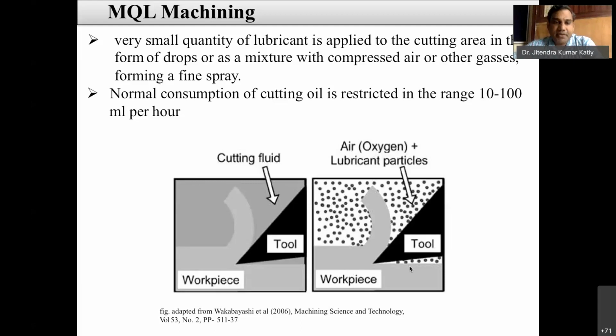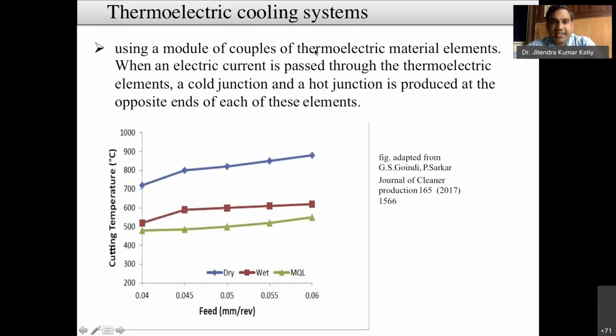So minimum quantity lubrication in terms of thermoelectric cooling systems is also very important. At the cutting temperature, you can see that even if you increase the feed, the cutting temperature is more or less the same in minimum quantity lubrication. That's why it is of great importance. In case of dry, the temperature range is very high, in flood cooling it decreases further compared to dry, but minimum quantity lubrication is better compared to both wet and dry. So that's why it is widely used nowadays.